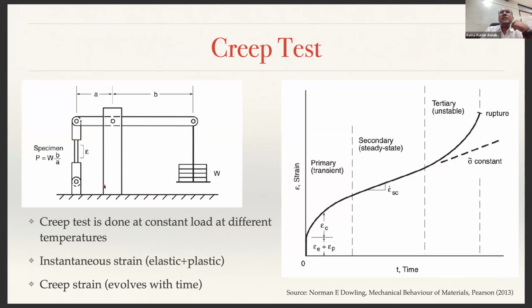So this is how a typical creep testing machine looks like. Very simple. A fulcrum based test, you will apply a constant load here, and this is your specimen, and you put a strain gauge to measure the strain here. For a constant load at a given temperature, you maintain this in a furnace so that the entire specimen is at constant temperature, and then you will have instantaneous elastic plus plastic strain depending upon the load that you apply, and then you will have primary creep, secondary creep, and tertiary creep, and then you will have rupture.